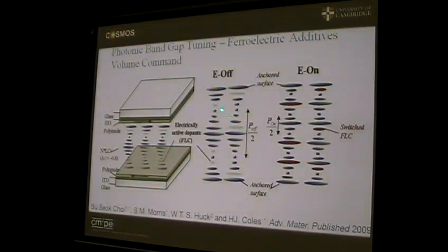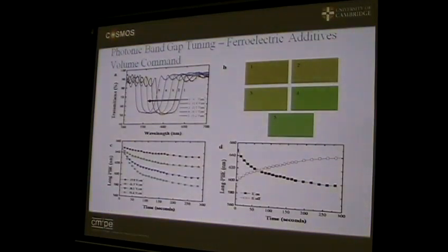And you switch throughout the volume the ferroelectric, and you do that for a very simple reason: you can switch a ferroelectric much faster away from the surface than you can at the surface. When you switch the ferroelectric, you switch the helix. And I've sort of drawn that so you see a pitch length that has decreased through the switching, through the twisting. So you actually twist the whole volume. How good is that? I think those sort of curves tell you, I'll show you.